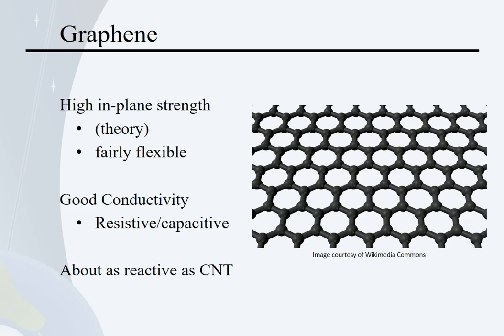Chemically speaking, they're about as reactive as CNTs. No one's demonstrated the self-healing mechanism, but I wouldn't be surprised if one was found. So, very, very comparable, which makes sense. They're both structures that consist entirely of carbon. The vast majority of that carbon is in these six-membered rings. Each of these rings is all double bonds. So, high electron mobility, strong bond, same material, a little different geometry. And that leads to some surprising differences in properties.